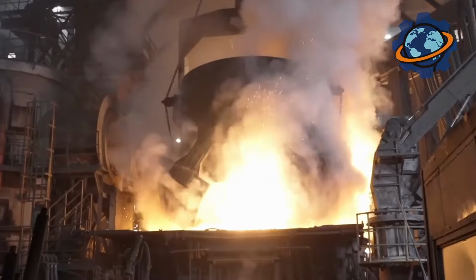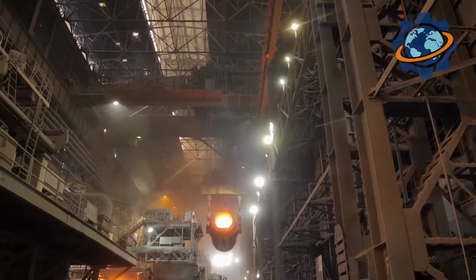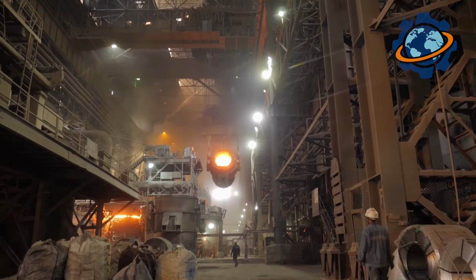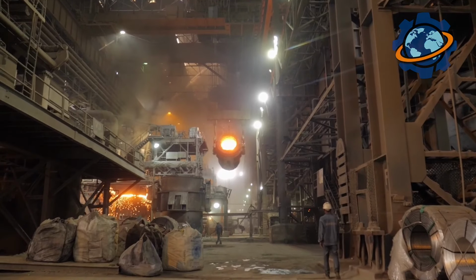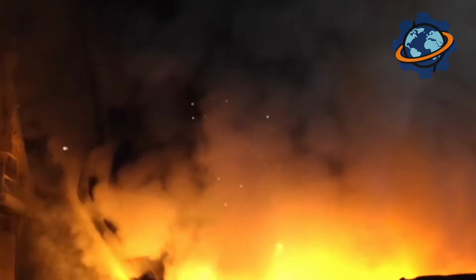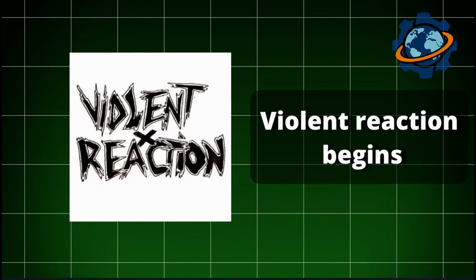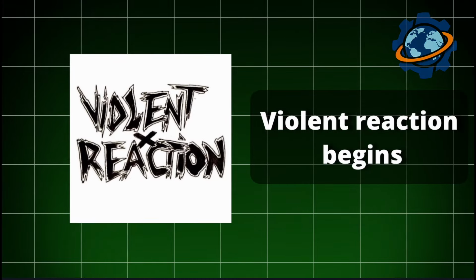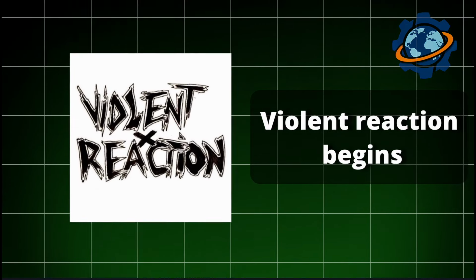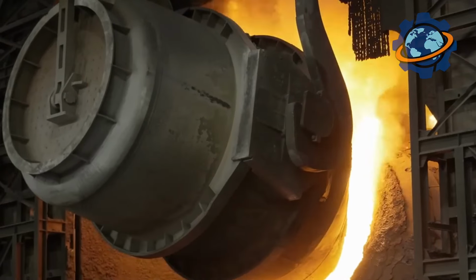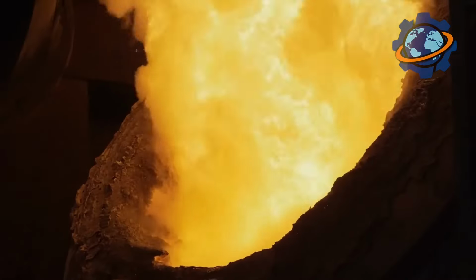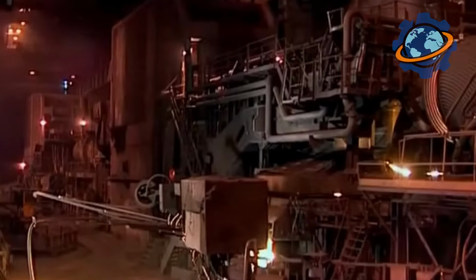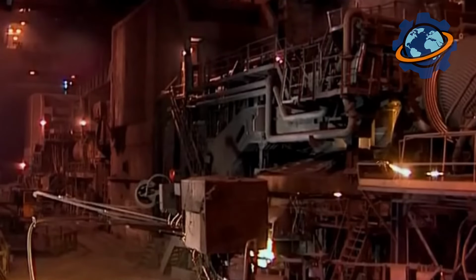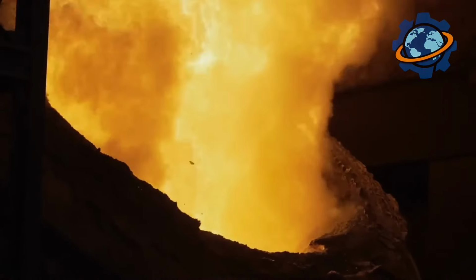An oxygen lance, a tube 20 inches in diameter, lowers from above. Oxygen flow begins. A jet of pure oxygen at 150 pounds per square inch pressure strikes the molten metal. A violent reaction begins as oxygen oxidizes carbon, silicon, manganese, and other impurities in the pig iron. These exothermic reactions release enormous heat, and temperature rockets to 3,200 degrees Fahrenheit.